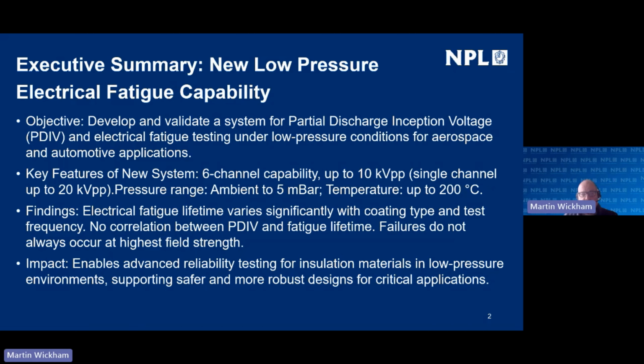And we're going to talk about how we've looked at electrical fatigue lifetime and how this varies significantly with coating type and test frequency. We haven't seen a correlation in any of the samples so far between PDIV and fatigue lifetime. And the failures do not always occur where the highest field strength in the samples are, and we'll clarify that later.